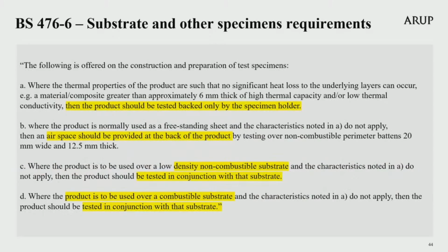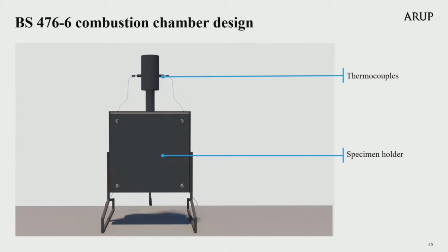Several options are then provided with regard to the preparation of the test specimen, and if it can rest directly on the specimen holder, or if it requires a substrate between it and the specimen holder. And these are all shown on the screen here. Prior to the test, the specimen holder is then firmly fixed in place as shown on screen. During the test, both the gas burner and the two electric heating elements are used, which I will explain later. The temperature output from the thermocouples of the flue gases in the chimney is measured throughout the test, with specific temperature measurements noted at set time intervals, which I will also describe later.